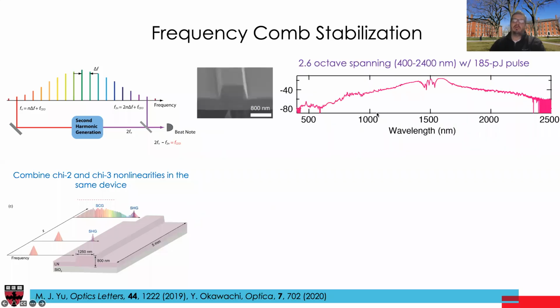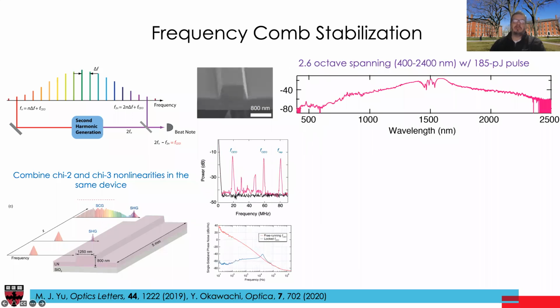So this shows broad supercontinuum generation in a lithium niobate waveguide of about 2.6 octaves, and this shows that this principle worked. We were able to detect the carrier envelope offset frequency. In this case, this was a mode-locked benchtop laser, I believe a fiber laser. It was done in collaboration with Alex Gaeta's group. So basically we used an integrated chip to stabilize big lasers. In reality, what we would like to do is to use this same waveguide integrated on our comb source to stabilize that comb source. The issue is that our comb source doesn't produce enough power to generate a supercontinuum that's as broad as we need.